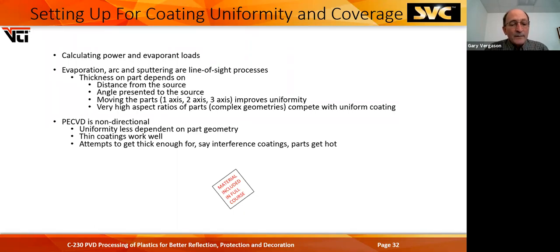PECVD is non-directional. It's a CVD process, so you can get down into nooks and crannies pretty well, although you still have issues with throwing power. Thin coatings work very well. And if you try to build up the PECVD thick, parts are going to get hot and they're going to get yellow.